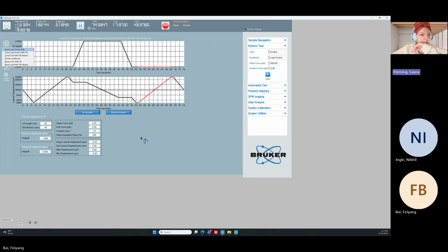Okay. And then basically, I showed you this one, constant load scratch. Never do this one. You always want to be able to correct your sample tilt. So typically I don't recommend you use that one. Instead, I recommend you use either constant load scratch with tilt or with tilt and retrace, depending on what information you want from the rest of the test.